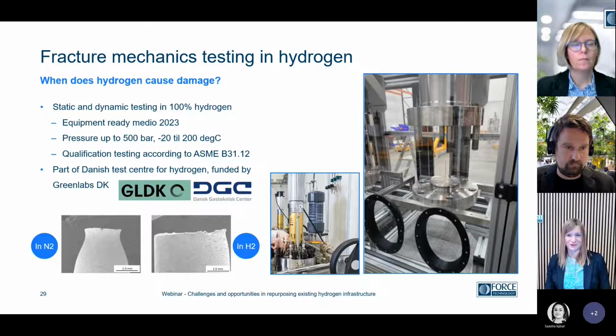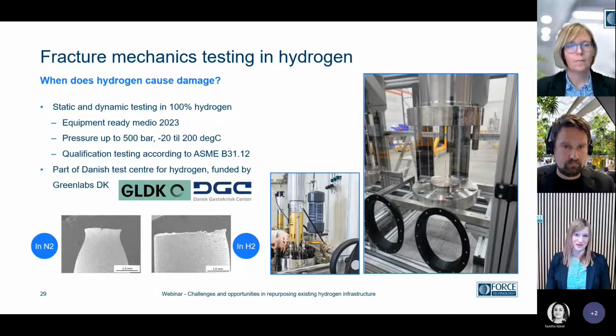Force Technology will have the first autoclave for fracture mechanics testing in hydrogen atmospheres in Denmark. And that is for us to contribute to this evaluation of repurposing potential of hydrogen infrastructure, because when does hydrogen cause damage? So during next year, we'll have static and dynamic testing in 100% hydrogen. We'll be able to test up to 500 bars hydrogen from -20 to 200 degrees Celsius. And this will also include the qualification testing needed by ASME B31.12. And that's making us part of the Danish Test Center for Hydrogen, together with Danish Gas Technological Center and funded by Green Labs DK.